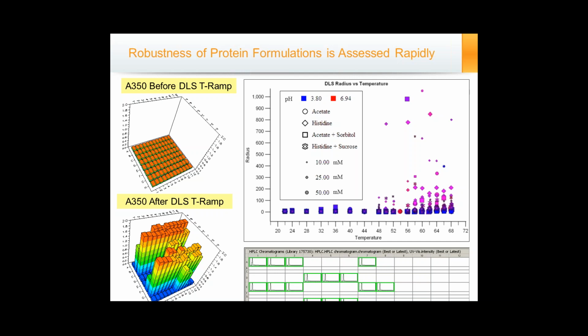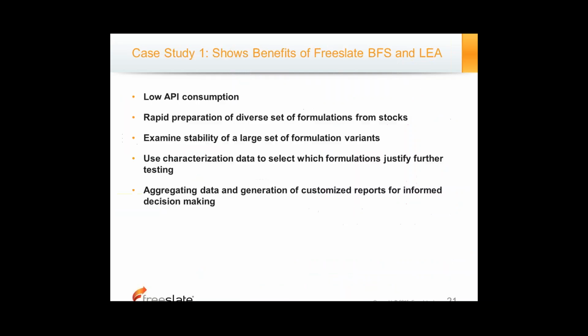We also have the ability to make multivariate plots, so you can see the radius is on the left, and then we have temperature on the bottom, and we can have a color map here for pH, and we have different ways of looking at the data points to help suss out what the differences are. And this is something that can be configured by the scientists and their teams. What's important to show here is that we selected only those formulations that are robust, and then we performed the SE-UPLC to verify that there's no presence of aggregates in those.